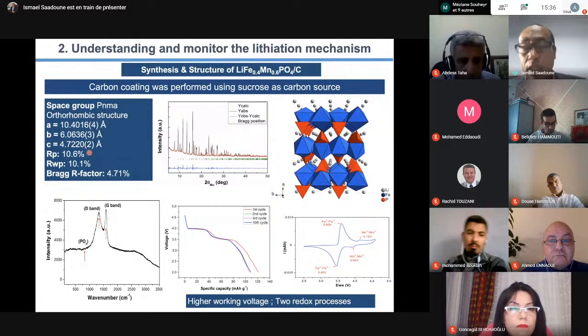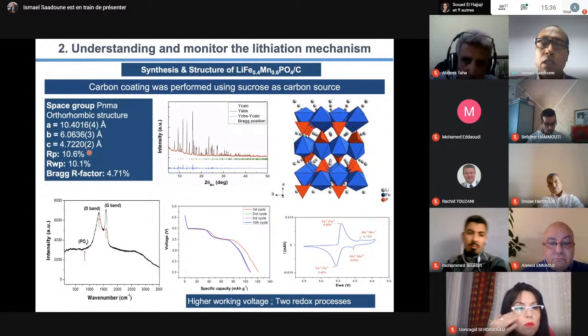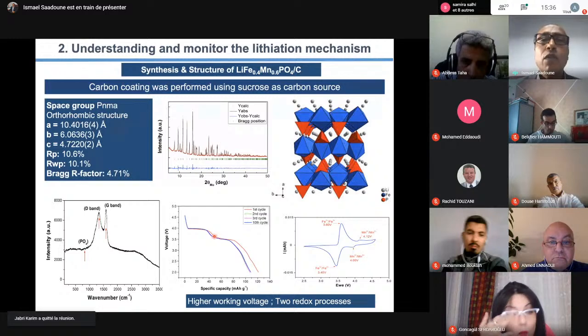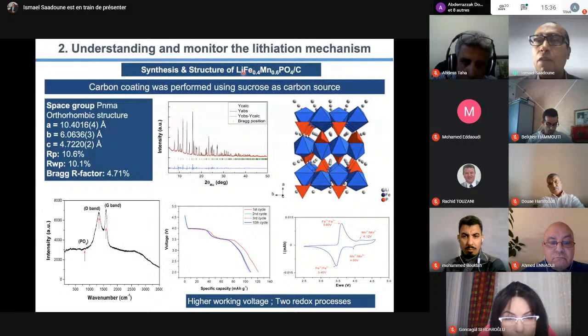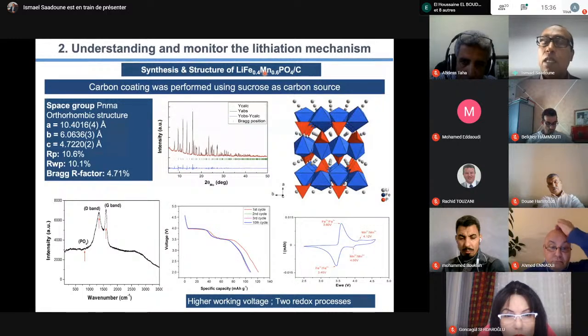Coming back to this in-situ characterization, with Ilham Bizza, who defended in 2016, we started to study this iron manganese phosphate. Remember LFP, we have this problem of low voltage, very low voltage. So we introduced manganese to increase the voltage, and if we increase the voltage, we can increase the energy density.